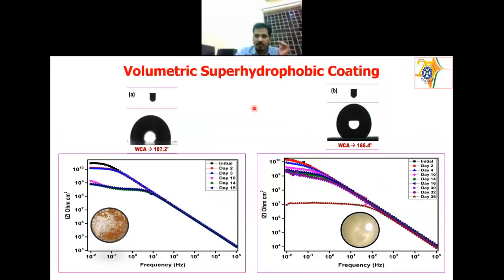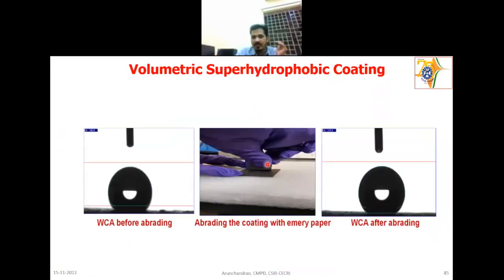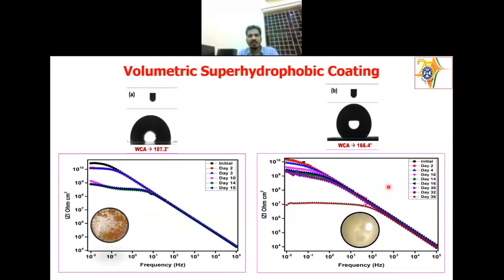That means when you scratch the coating, here I am scratching the coating using emery paper, and I found that it still has a quite high water contact angle. It is even increasing after scratching. So even in the depth of the coating it is super hydrophobic, with the presence of the pigments we added in the coating.